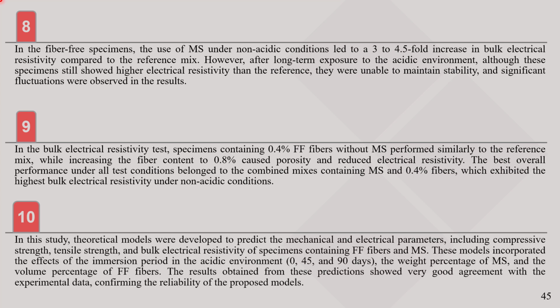Regarding volumetric electrical resistivity, under non-acidic conditions, using microsilica alone increased resistivity 3 to 4.5 times compared to the reference sample. Fibers alone did not have a significant effect, but when combined with microsilica, they helped maintain resistivity over the long term and greatly improved electrical stability compared to the reference.